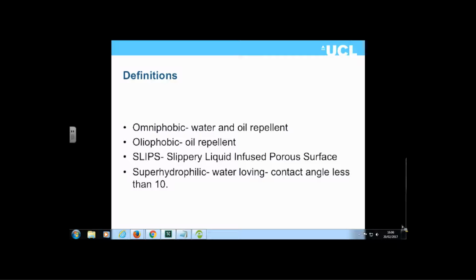Now, to have a self-cleaning surface, you either want to be superhydrophilic or superhydrophobic. If you're superhydrophilic, and this is an example with commercial window glass, such as Pilkington Active, that has a titanium dioxide layer on the surface, and when activated with sunlight, any water that impacts on the surface will form a sheet, and that sheet washes down dirt uniformly. If you have a superhydrophobic surface, the water on the surface forms a ball and it rolls across the surface, and this surface motion helps to give you the self-cleaning activity.